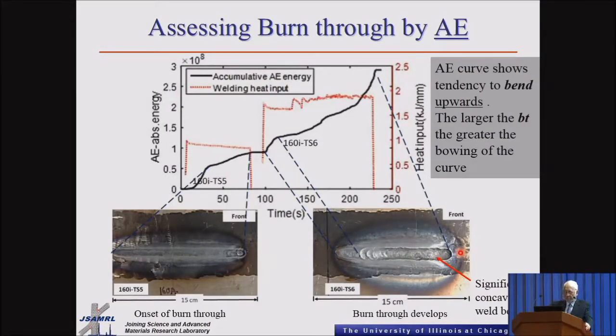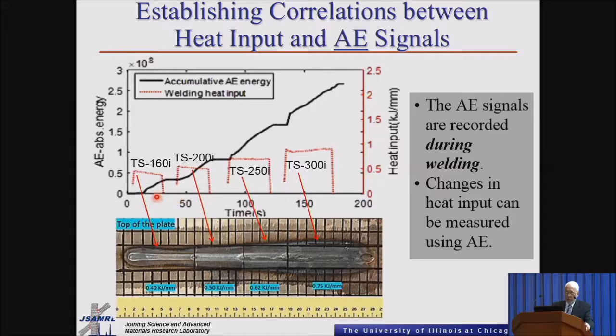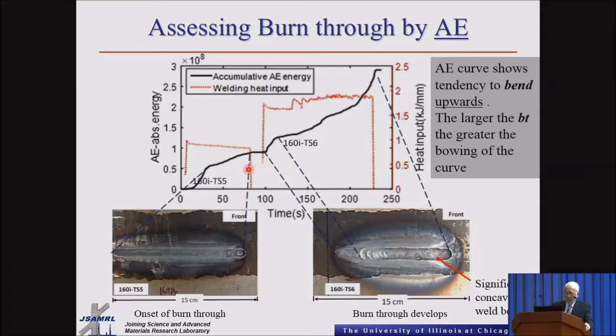What about now the possibility or the occurrence of burn through? If we go back to the previous graph in here, those slopes are pretty much linear. I just want to call that to your attention. The slopes are pretty much linear as you increase the absolute energy of the acoustic emission. Now, if you look very closely on this one here, there are some areas in here that are in between. So it could be straight, but it's trying to do some kind of curvature that tries to bend upwards. In this case, right over here, you can see there is a larger curvature, and we would try to correlate that with this type of depression.